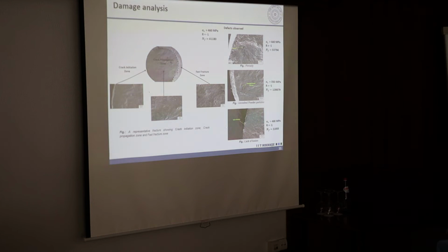Coming to the damage analysis, all the specimens that have been tested have been analyzed using SEM to evaluate the crack initiation, propagation and fast fracture zone. You see most of the cracks initiated from the defect region, and these are the few defects that have been observed: porosity, unmelted powder particles and lack of fusion. Similarly, all the specimens contain some sort of defects, and we quantified those defects using some statistical tools.